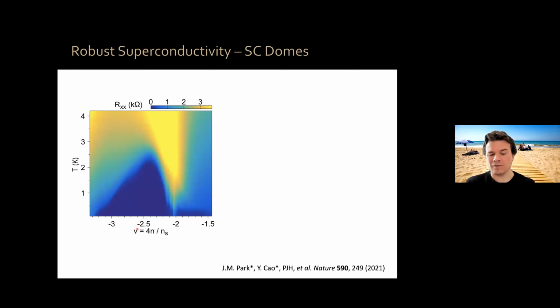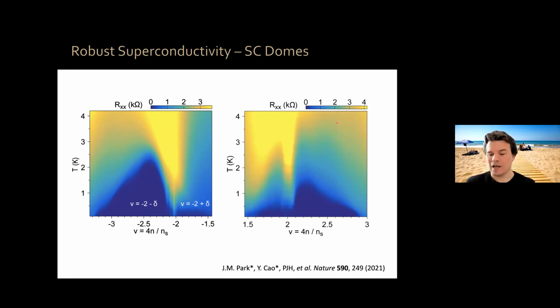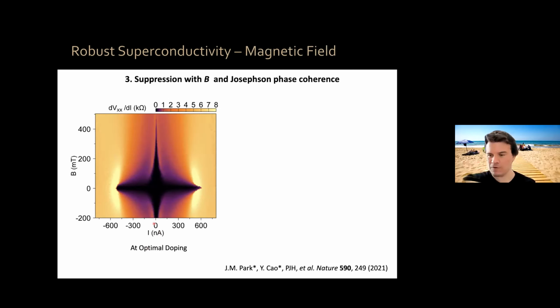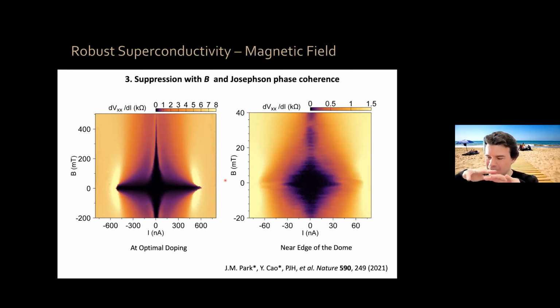This is resistivity versus temperature and filling factor. You have the superconducting domes at -2 - delta and -2 + delta. Delta is the extra doping. For electrons, you also have these domes. In a magnetic field, the superconductivity gets suppressed. If you are at optimal doping, where the system is uniformly superconducting, you just suppress it by a perpendicular magnetic field, initially fast on a 100 millitesla scale, and then it has this long tail going up to about half a Tesla. If you go to the edge of the superconducting dome, where the system breaks up, due to disorder, into superconducting islands, then you can find Fraunhofer-like interference patterns, which tells you that there is Josephson phase coherence through the system. This firmly establishes that this is a superconductor.